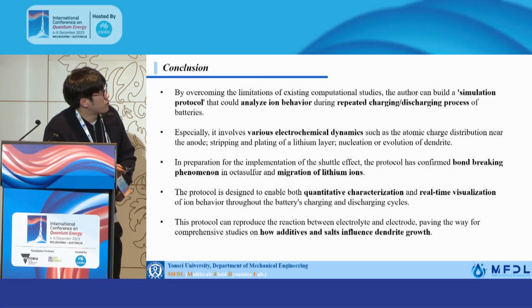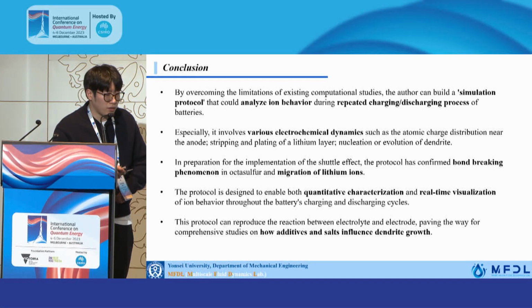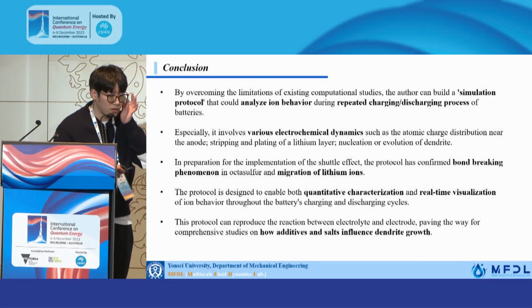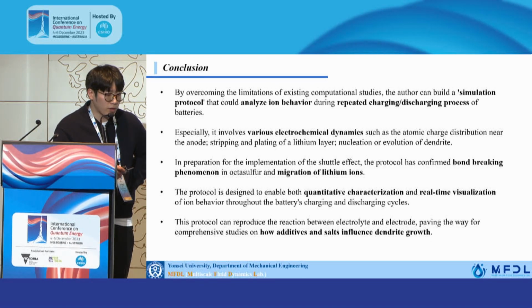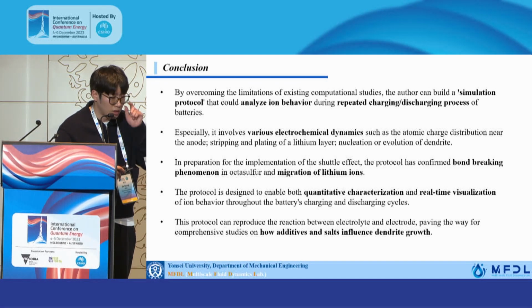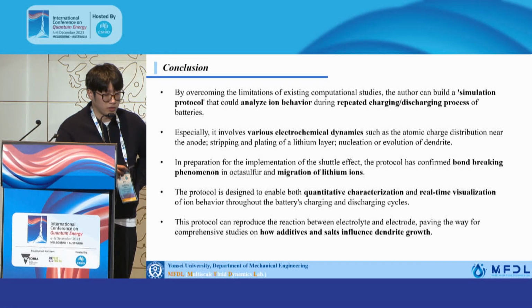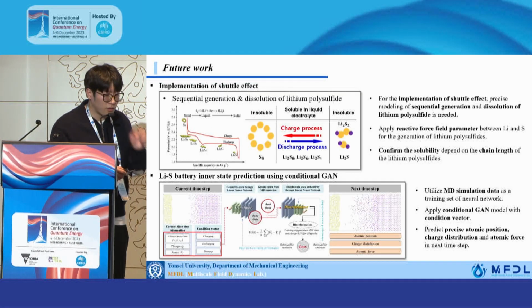And here is the conclusion. By overcoming the limitation of existing computational studies, we can propose the simulation protocol that could analyze the ion behavior during the repeated charging and discharging cycle. And this protocol can reproduce the reaction between the electrolyte and electrode, paving the way for comprehensive studies on how additives and salts influence the dendrite growth. And here is our future work.